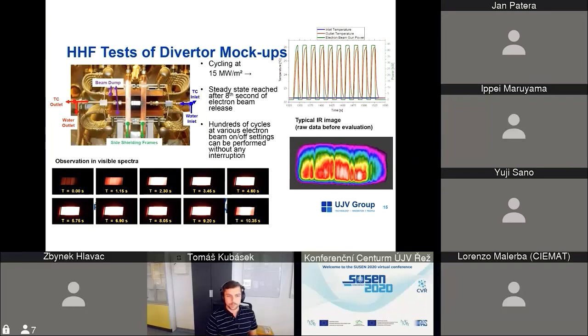Here you can see the cyclic load that was applied to the tungsten mockup. And here is a slideshow, basically, of the mockup as it was being irradiated. I think, if I'm not mistaken, we reached surface temperatures of 2000 degrees Celsius.